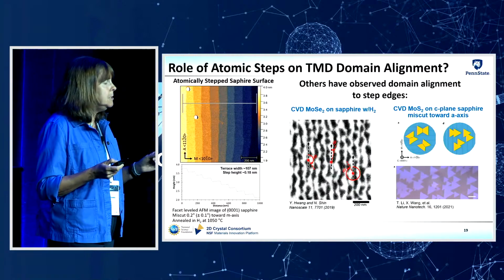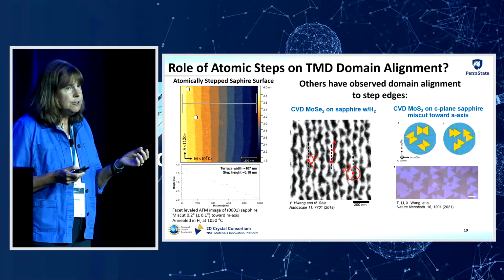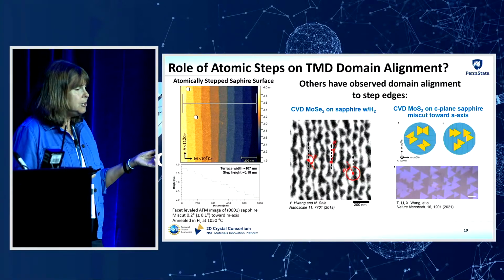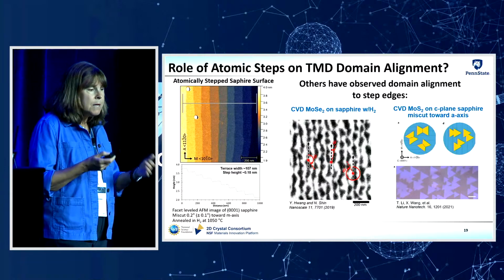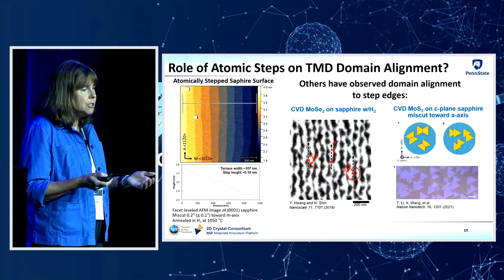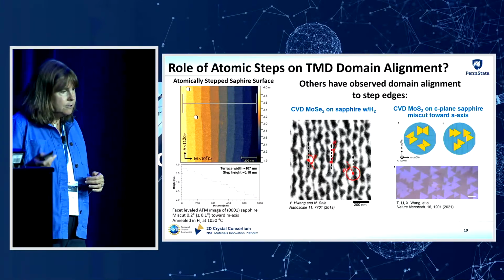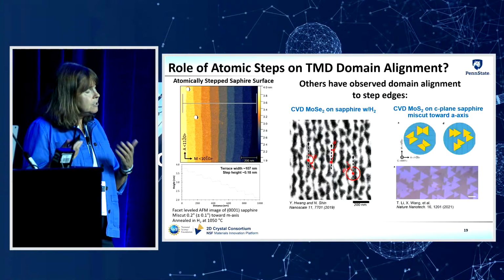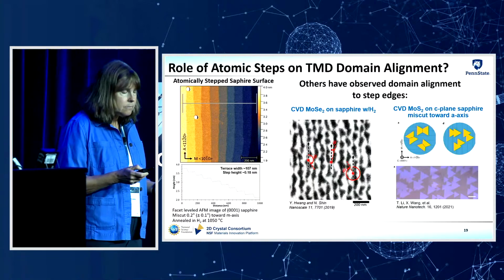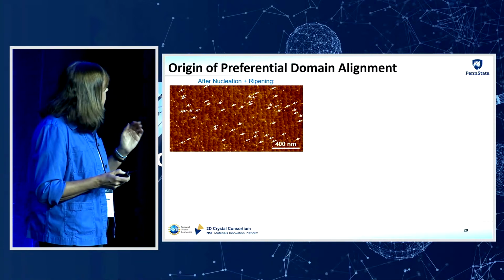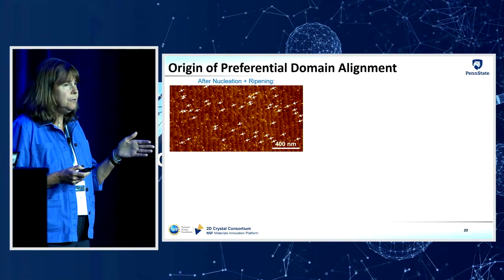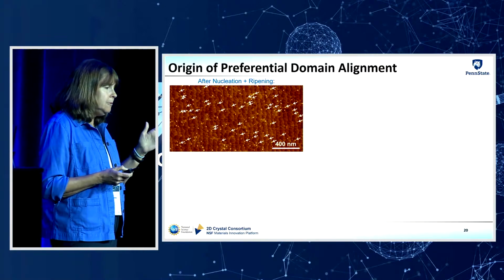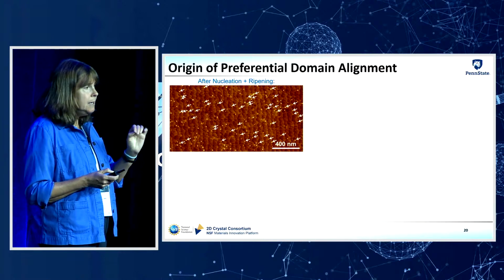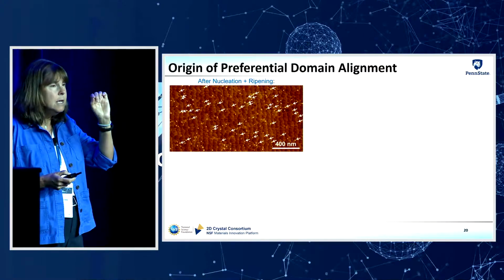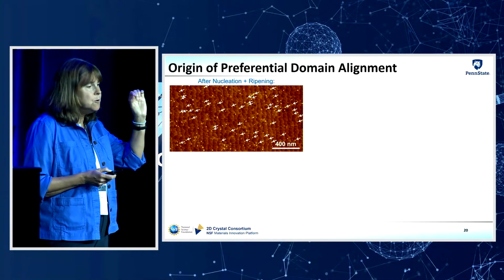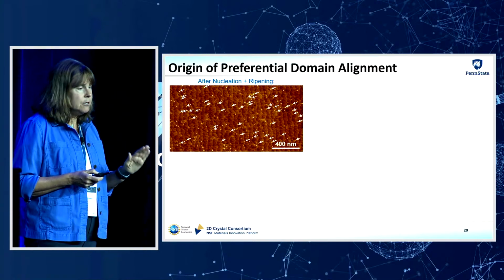And it's previously been shown that steps on the sapphire surface can serve as sites for nucleation of our TMD domains. These are just two examples from the literature for molybdenum diselenide and also for molybdenum disulfide, where they saw a preferred orientation. So we wanted to take a closer look at this, and we can do this using our three-step process. We can stop the growth right after nucleation and ripening when we just have these tiny little islands, and we can look at where those islands form relative to the step edges on our sapphire.